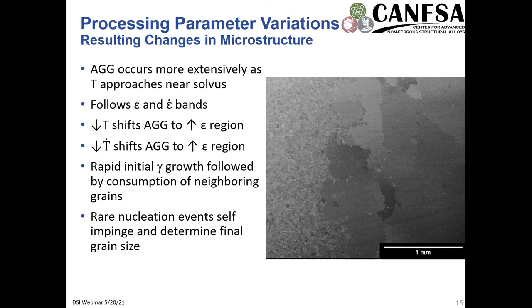And so to summarize a lot of the results, this abnormal grain growth occurs more extensively as we approach the gamma prime solvus, and it follows these horseshoe bands of strain and strain rate within the material. As we decrease the temperature, this shifts the abnormal grain growth to a higher strain regime. And as we decrease the heating rate, I should note the temperature and the heating rate are within the post-deformation supersolvus heat treatment, so that's not during deformation, that shifts these regions to a region of higher strain, perhaps typical of the recrystallization they conventionally think of. This rapid initial gamma grain growth occurs to consume neighboring grains that have stored energy. And then once you have such a huge size discrepancy between the neighboring grains and the abnormally large grains, growth progresses, and you can end up with columnar looking grains in some situations.